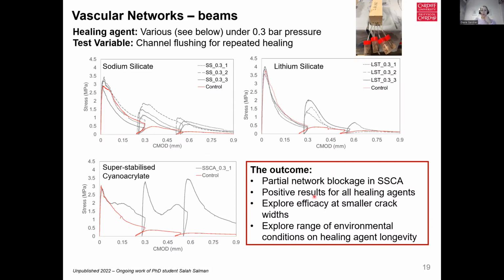But in actual fact, what we did notice was that we had some blockage in some of the channels for our super stabilized cyanoacrylate. We did get positive results for all our healing agents. And what we wanted to do, because we were cracking these to 0.3 millimeters each time and opening up again to 0.3, we really wanted to make sure that we could achieve similar sorts of healing at the smaller scale, so crack widths down at 0.15 millimeters.